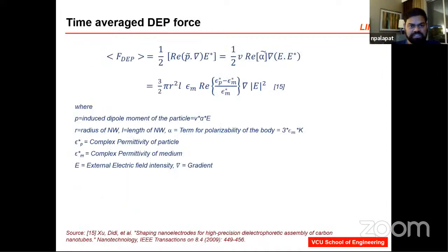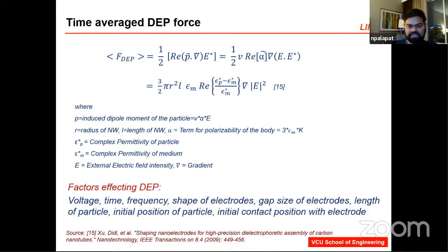Coming to the principle of the DEP itself, this is the equation involved. I'm not going to go much into detail, but what I will highlight here is there are some parameters that you can control to figure out how many nanowires you want at a location, at what region. That is the permittivity, which defines the ability of the particle to be polarized. And further, we have the voltage, and the solution itself, how distributed the particles are. These are several of the factors that can affect how your particles deposit in those locations. Out of these, what I've focused mainly on are the voltage, time, and frequency. These three parameters were found to influence more how your nanomaterials are deposited.